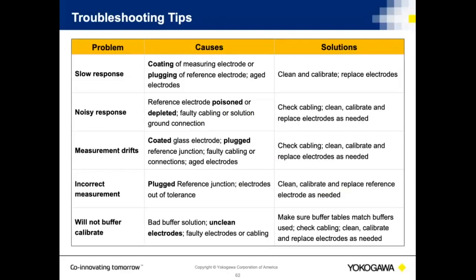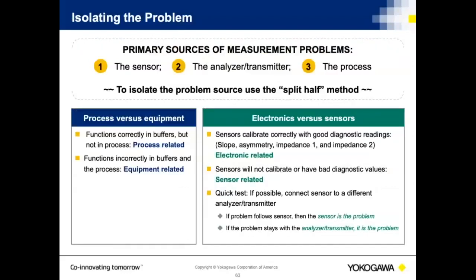And basically it tells you clean and calibrate. That's the first thing you do with these analyzers and these pH probes. Make sure they work in pH buffer solutions. If they don't work properly in pH buffer solutions, they will not work well in your process. How do you determine that? Well, again, it's the buffers.